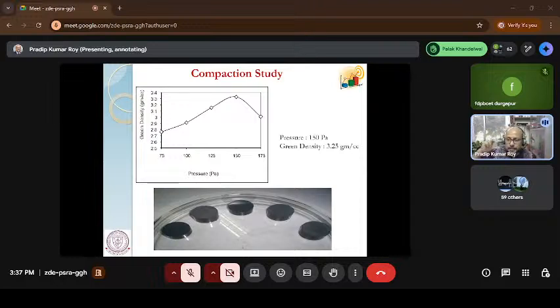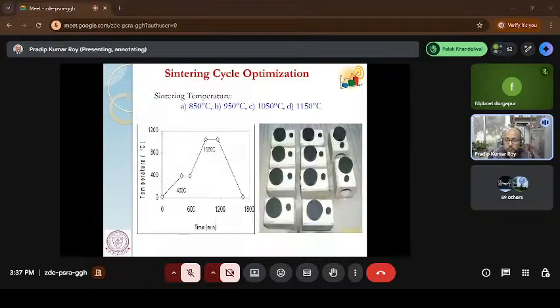So if we increase the pressure, the particles will compact each other. Density is mass by volume. So if the particles are compacting, your volume is decreasing, your mass remains the same, that means your density is increasing. One time will come when the pressure is at maximum, and when you release the pressure, the material will bounce back. That means the volume is again increased, so when the volume is increasing, the density is decreasing. So that is the optimum pressure you require to get the optimum green density of the material.